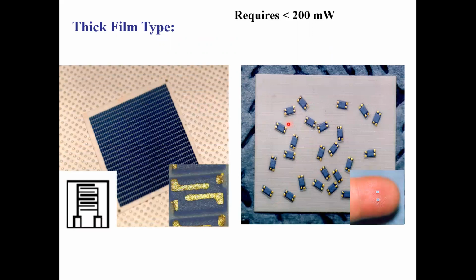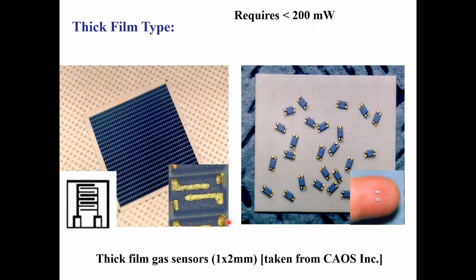So again, you can see the actual sensors. You can see the size. It's a 1 by 2 millimeter type sensor with these gold pads. You can see 2 for heating and 2 for measuring resistance changes. These are usually printed on top of an interdigitated gold electrode on a piece of alumina. At high magnification, you can see the gold fingers in that sensor.